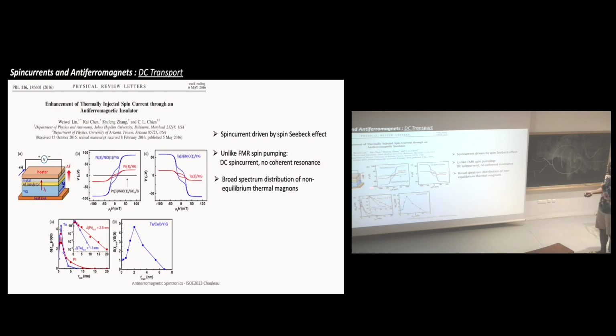And there is a whole discussion here because, as you can see, this is enhanced. So we could say that if there is NiO, it is enhanced, but it's not so easy actually, because what they have done, they went above the NiO temperature, and you can still see some kind of enhancement. So there is not only the antiferromagnetic part, but there is also spin fluctuations, which basically help the thermal magnons to go through. So it's kind of tricky. But you see, it's about the same time. So all this work really triggered the field of antiferromagnetic spintronics in oxides.